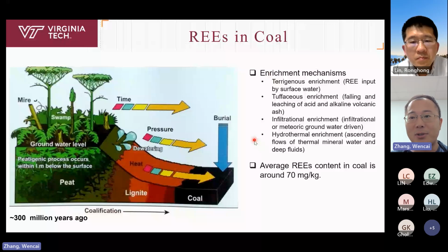For example, the terrigenous enrichment, tuffaceous enrichment, infiltrational enrichment, and hydrothermal enrichment. So due to these mechanisms, the average rare earth content in coal is around 70 milligram per kilogram. This is on a whole sample basis. Because coal contains a lot of organic matter, if you combust the coal and get the ash residue, the rare earth content can go up to around 500 milligram per kilogram.